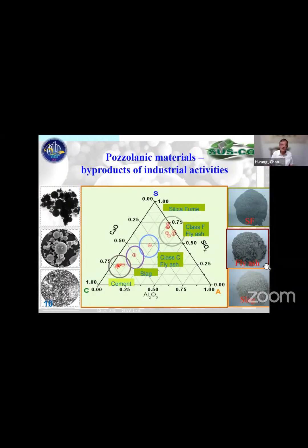So looking at the ternary diagram of SiO2, Al2O3, and CaO, you will see the relationship of class F fly ash, class C fly ash, and slag. In Indonesia, there is also a lot of blast furnace slag, which is also very useful. And cement here, and silica fume here. Usually for ultra high strength concrete we need silica fume, but if you use class F fly ash, you can have a similar result.